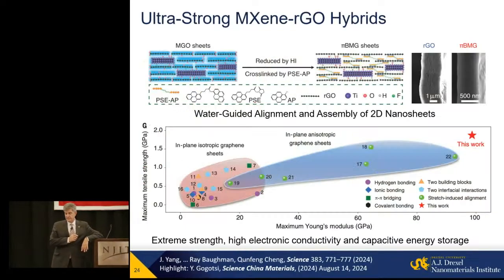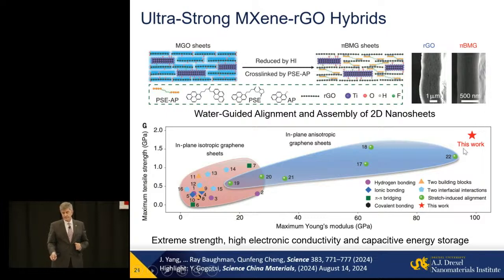This is a more recent paper, coming from the Chinese Academy of Sciences and Ray Baughman from the University of Texas at Dallas. They combined MXene with graphene oxide, similar to what he did, reduced it with HI, and also added an organic molecule that bridges the layers, and dried it. Room temperature material. The mechanical strength is 1.8 gigapascal. This is twice the strength of steel. Now imagine, you make at room temperature from solution a material that has twice the strength of steel.